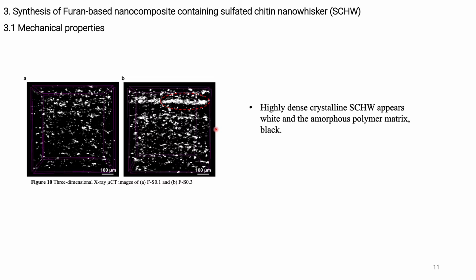However, when we increase the filler up to 0.3, the hydrogen bonding between the nanofillers can impede the dispersibility of the filler, as we can see a certain level of aggregation here. So in this case, the fillers seem to fail to mechanically reinforce the nanomaterial in terms of the tensile strength, but just increase the elongation at break.